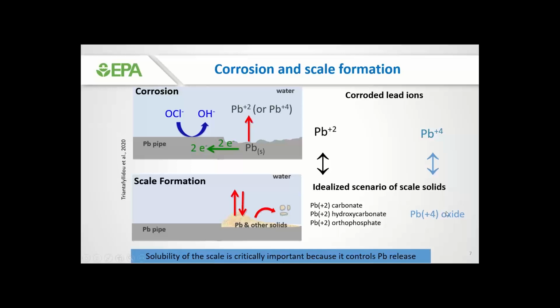like PbO2 represented here. So the solubility of the scale that forms is really critically important to metal release, because that's what really controls lead release. In my schematic at the bottom, you see those two red arrows coming outward from the scale and inward to the scale. This is the equilibrium and the balance with the water that's flowing through, and that's really controlling lead release. You also see another arrow disrupting the scale and releasing particles into the water.